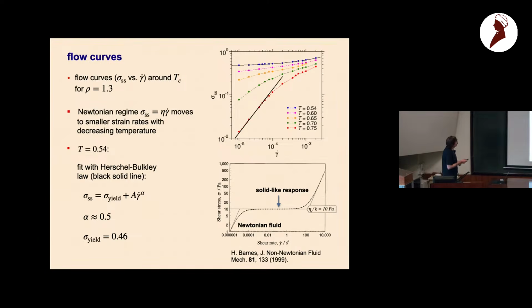And at the lowest temperature here, we get the typical Herschel-Bulkley behavior, where we can read off via this fit the yield stress, and the exponent is here around 0.5.